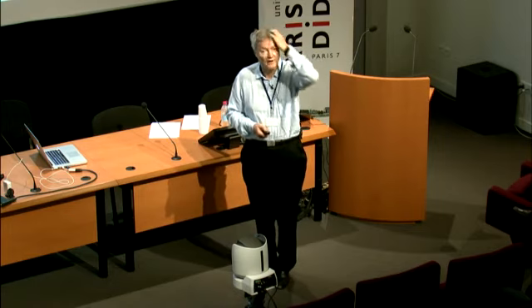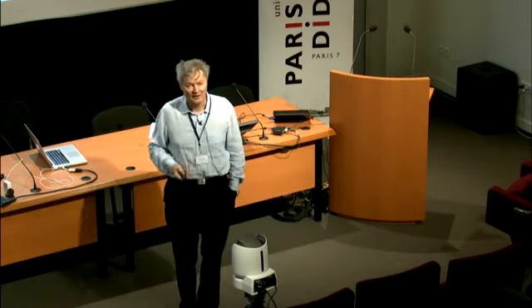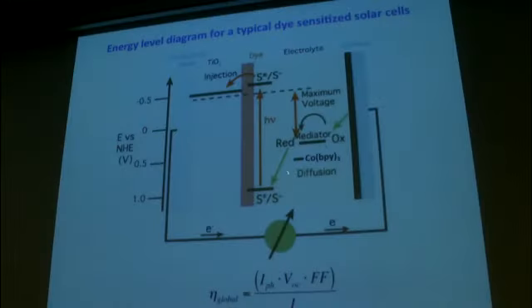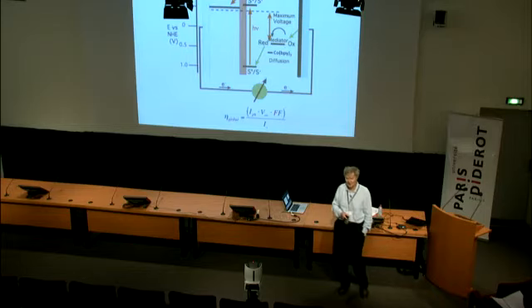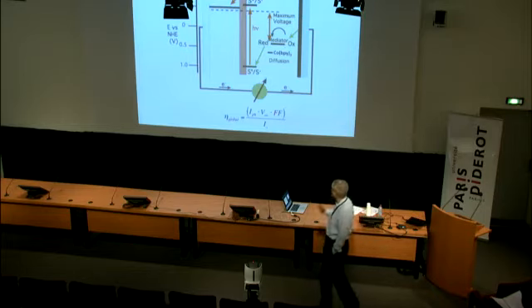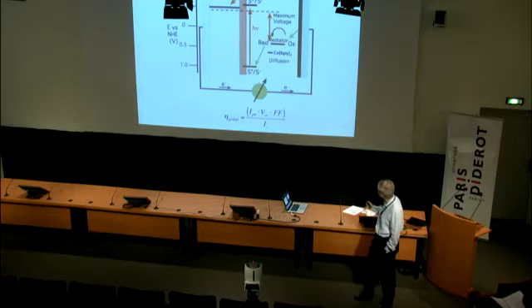And of course, that is a cost. The VOC goes down. It's very hard in dye-sensitized solar cells that give good currents to get more than 700 to 800 millivolts VOC. That's the voltage you get. But with the cobalt systems, we have been varying the redox potential. It turns out that 0.2 eV, 200 millielectron volts, is enough driving force to regenerate the dye fully. So actually, the loss can be reduced significantly.